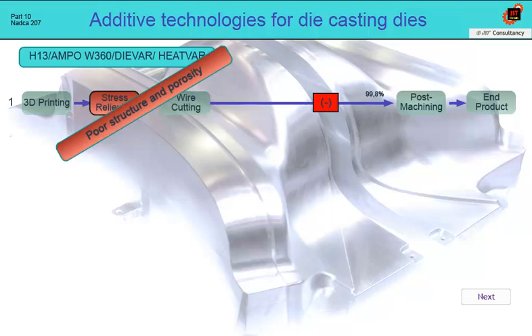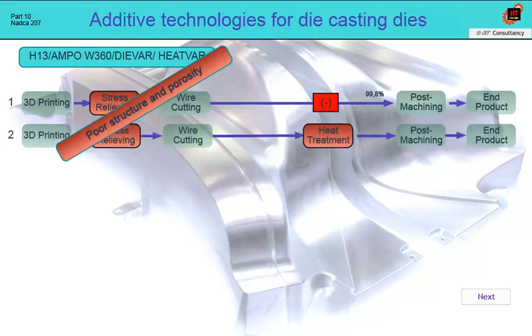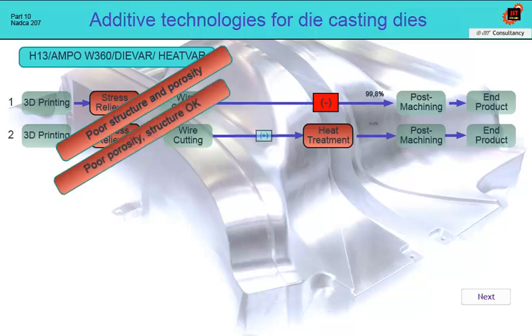The second process flow already applies vacuum heat treatment. Since there are no known verified recommendations for quenching and tempering, probably the least evil is to apply the same heat treatment procedure as for the compact material according to NADCA 207. This process flow changes the brittle structure after 3D printing to a tough structure with double or triple tempered martensite, with some residual austenite. The only problem will be how the porosity of the print affects the thermal fatigue resistance.